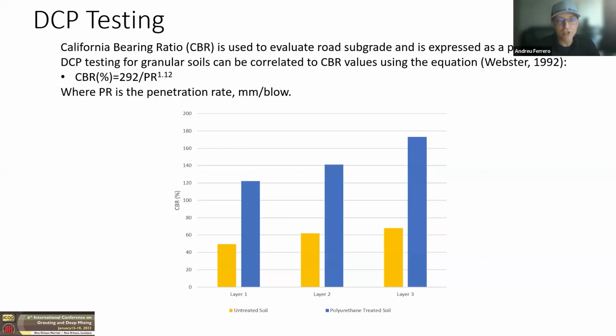California bearing ratio is generally used to evaluate road subgrade and is expressed as a percentage. I used a correlation from Webster to estimate the CBR percentage from the penetration rate, which shows that we got a substantial increase in our CBR over the untreated soil.